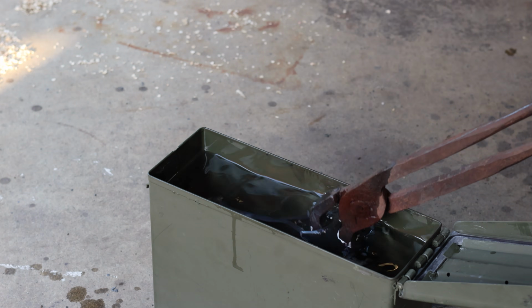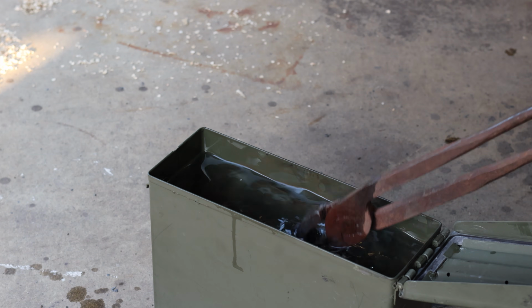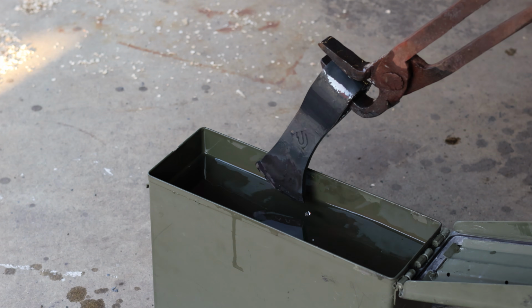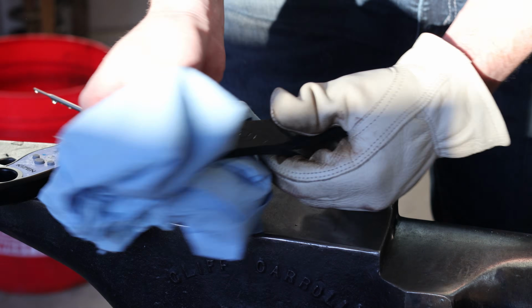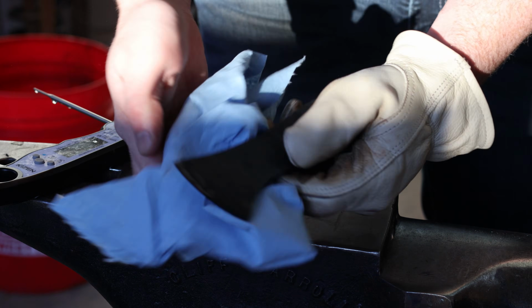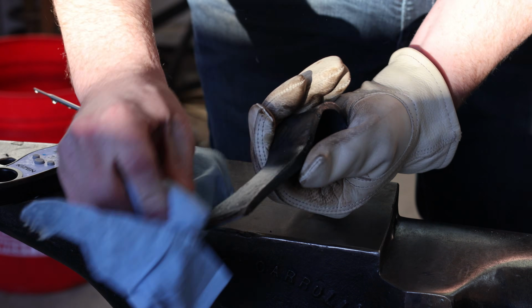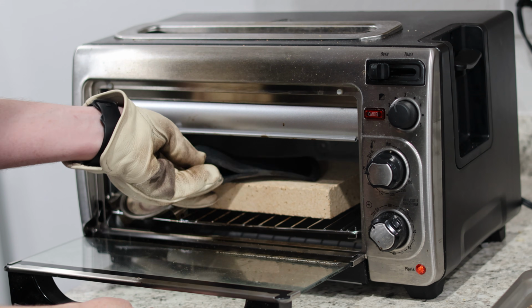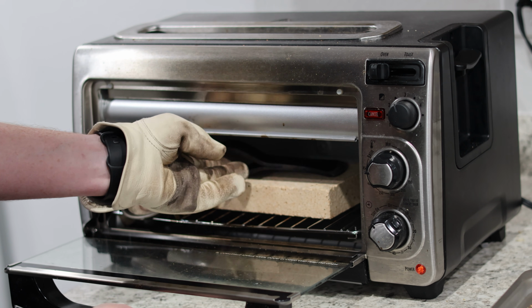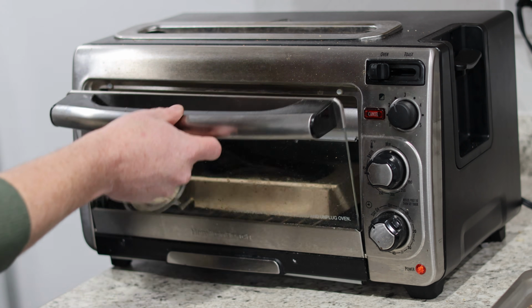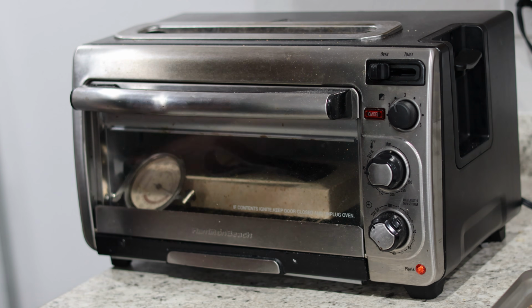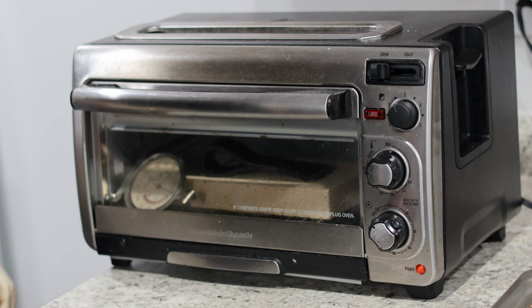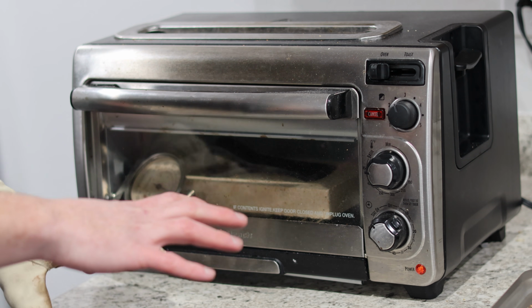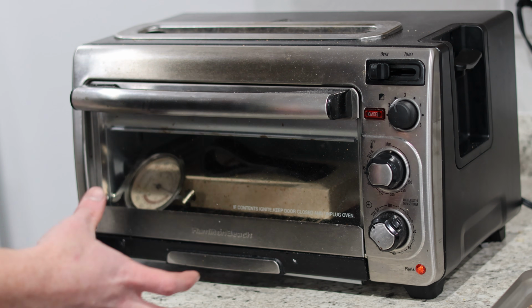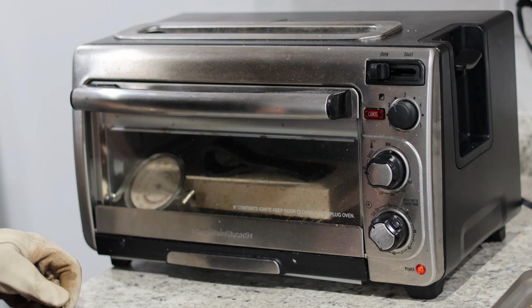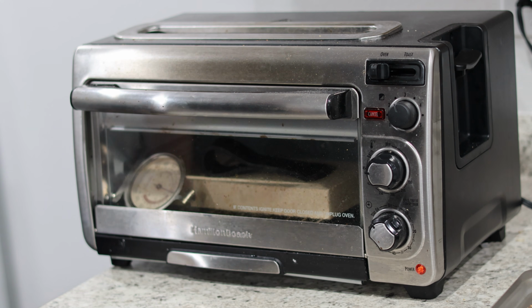I'm just gonna cool that head off completely now. All right, get this wiped down. And then I'm going to take this and put it immediately into a preheated toaster oven for a tempering cycle. I'm gonna leave this in here for about 2 hours at 400 degrees. That's gonna temper and reduce the hardness and the brittleness in the edge. That was the result of the quench. And in the meantime, we're gonna go work on the handle.